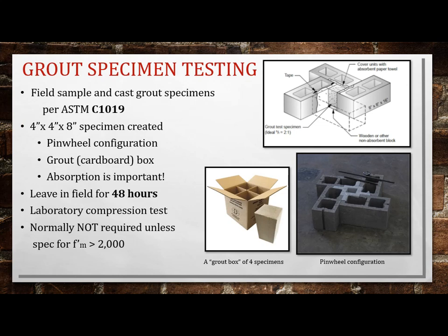So with grout specimens, here's another technique. There's two ways that you can make field grout samples, and it's covered by ASTM C1019. The two pictures on the right show a pinwheel configuration. You actually use CMU block in the field. You configure them so the space in the middle is 4 by 4 by 8 inches. You fill that with grout, rod it in a specified manner, and leave it for 48 hours undisturbed. Bring it back to the laboratory, cure it for 7 to 28 days, and do a compression test.